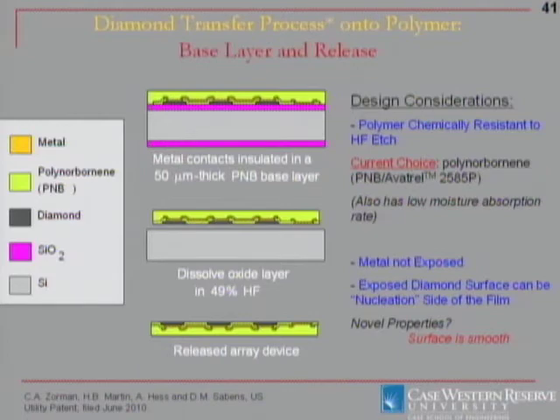That's shown as this darker yellow, and the lighter yellow is the polymer. This is done, of course, in a series of microfabrication steps, which I can't go through now. The key here is that the polymer, polynorbornene, is resistant to hydrogen fluoride etch, which is what we're going to use to remove this purple layer, the silicon dioxide layer, to release the device and now get diamond onto the polymer. And the metal is, of course, hidden in here, so we have a true diamond electrode in a polymer.